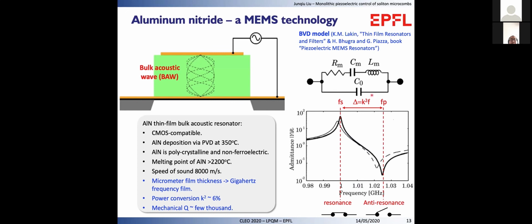The frequency response of the aluminum nitride bulk acoustic resonator is equivalent to the BVD model of an electronic circuit with inductor, resistor, and capacitor. When sweeping the AC driving frequency of the resonator, resonances and anti-resonances are observed. The resonance has a high admittance and a low impedance, which corresponds to a closed circuit. The anti-resonance has a low admittance and high impedance, which corresponds to an open circuit. On the anti-resonance, the energy is dissipated in the bulk acoustic resonator. The frequency separation is determined by the K-square, which is the power conversion efficiency, times the center frequency.